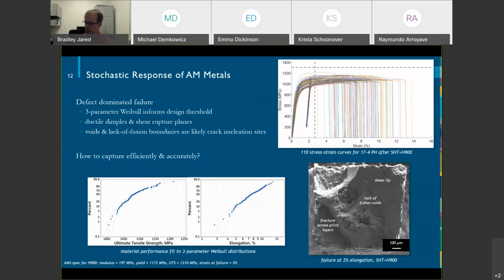But the real key here is the fact that there's a very wide distribution and spread in the data of the stress strain curves of this material, right? So typically as a mechanical engineer, I often think about materials having a property, right? It's got a modulus or a yield strength or an ultimate tensile strength or whatever. And it's always true, but in additive, we have these things like defects and surface finishes and microstructure variations. And what happens is we have a much larger spread in the material data. I have some data, I don't think I have it here, where a wrought curve is pretty close on top of each other, right? And so we start thinking about how we have distributions.